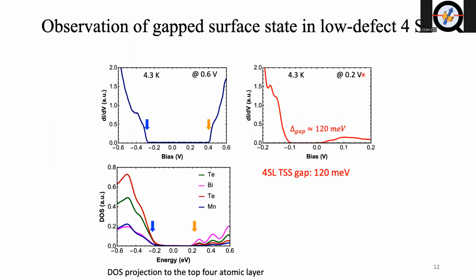So the Dirac point was defined as so. There is not an exact Dirac point because after we turn on the magnetism, we will open up a gap at the Dirac point, but the Dirac point is still defined as before turning on the magnetism. But anyway, here we see that the Fermi level lives within the gap. So the Dirac point should be somewhere in the middle of the gap.